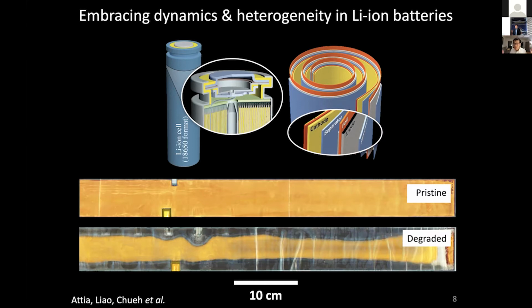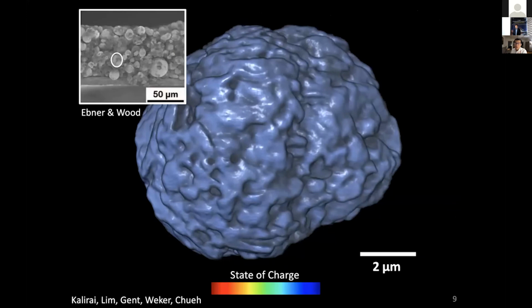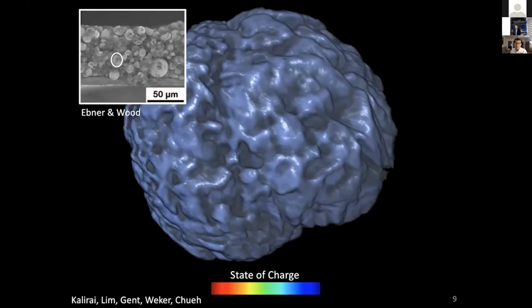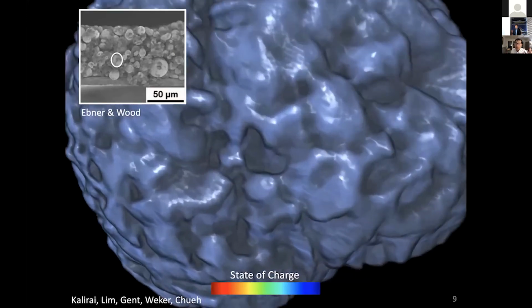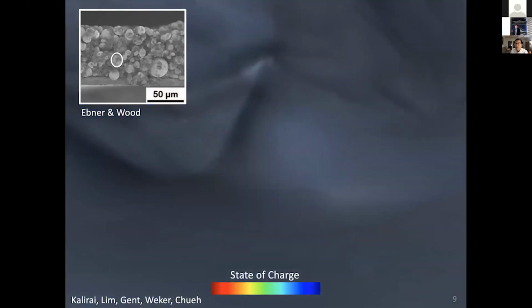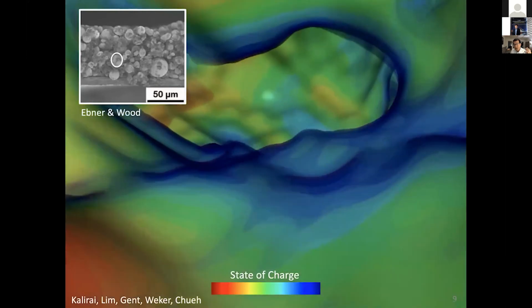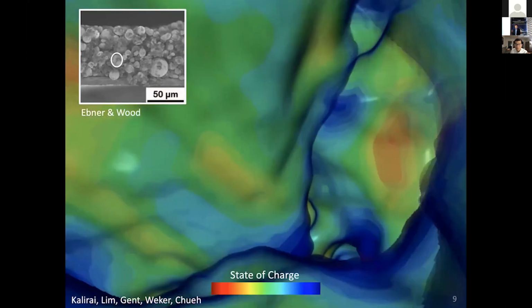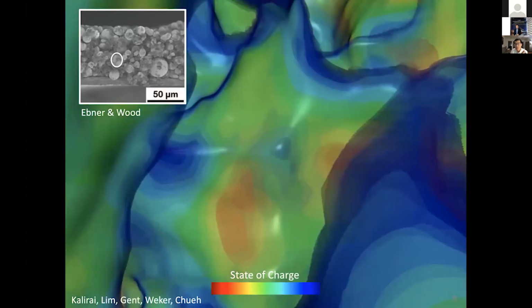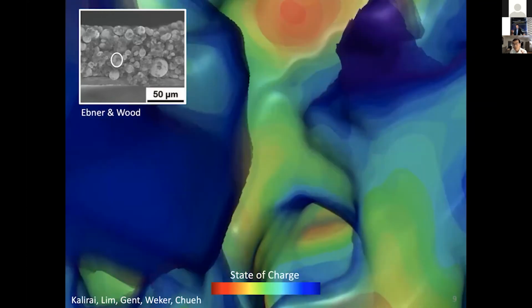And this is done just with an optical inspection of the electrode sheet. The scale bar is 10 centimeters. If we zoom in a little bit further and we look at the tens of micron length scale, we can look at an agglomerate. This is a battery positive electrode cathode particle. And here I'm showing the microstructure as elucidated by synchrotron tomography. And the color you're seeing here is actually the local oxidation state at the mesoscale.